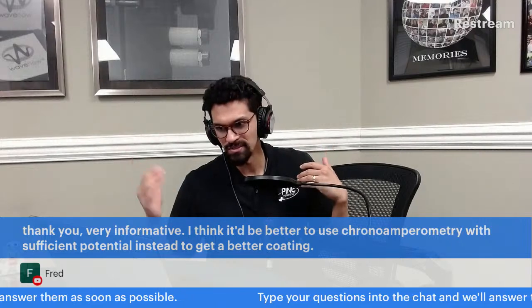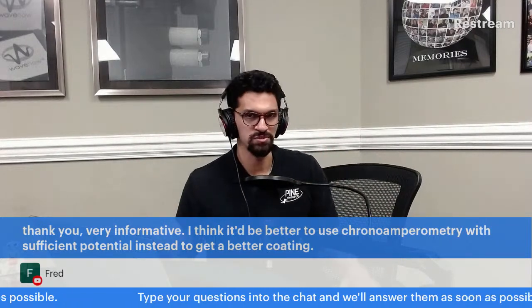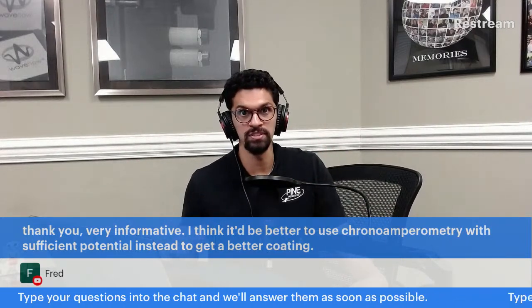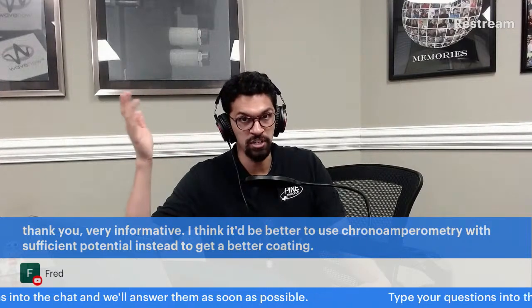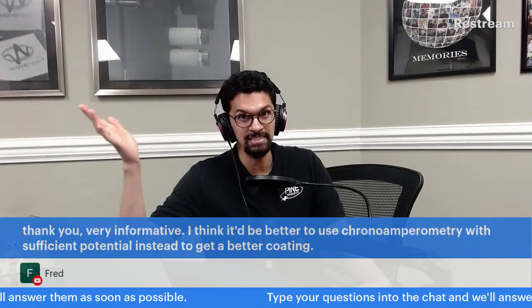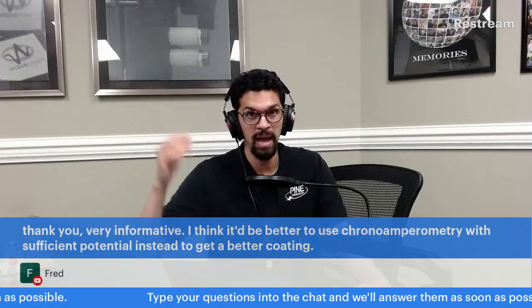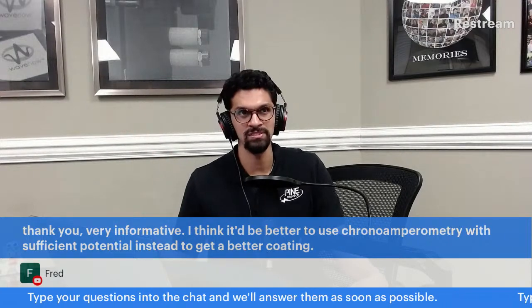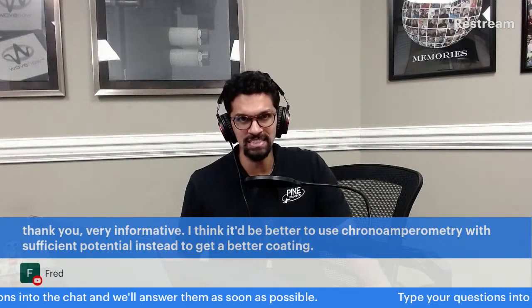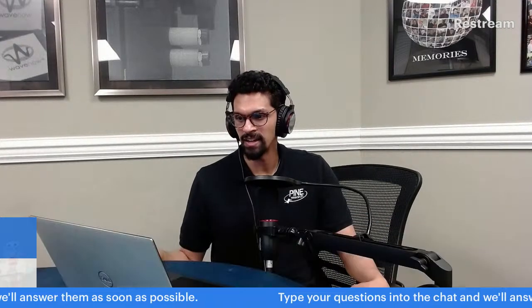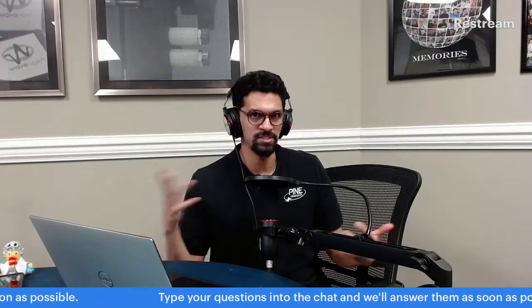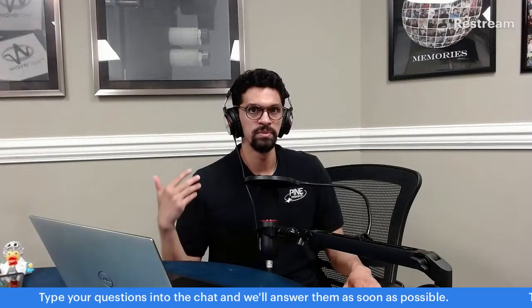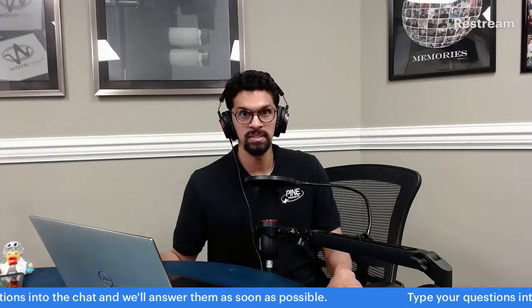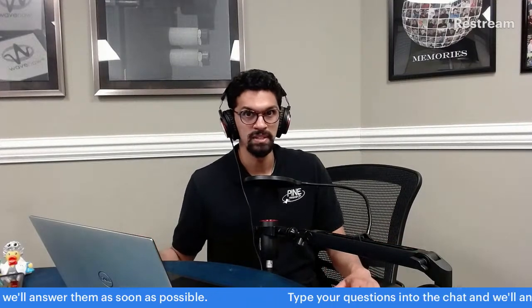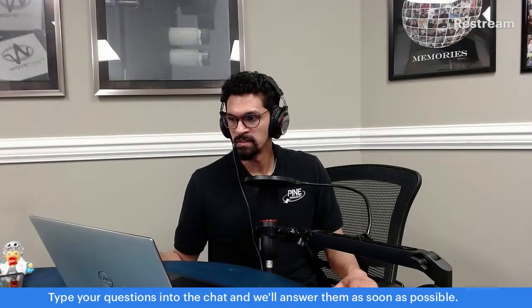So the surface, the counter electrode, the concentration of your species, the electrolyte, the solution resistance. Sometimes if you're applying a lot of current, you can actually get heating in your solution. I mean, that can also happen, and that also changes things. So it's definitely an engineering task to try and optimize the parameters to have uniform metal deposition. But a lot of people do it, and it just depends on how detailed you need it to be.